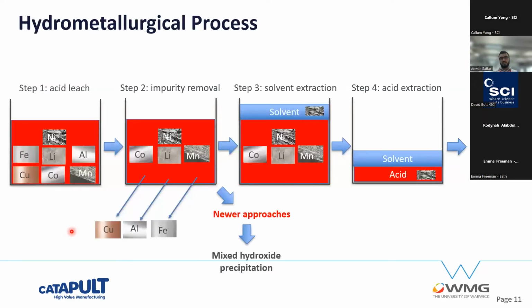So after you get the black mass, the next step is the leaching step. It's known as the hydrometallurgical recovery. So the first step is you leach it in acid. You put the black mass into acid, and then the metals all dissolve into the acid. The next step is you remove the impurities, things like the copper, the aluminium, the iron, and whatever else there may be in there.